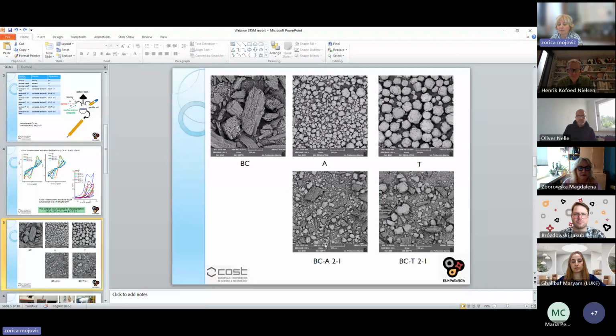These are the results of SEM analysis, and we can see the biochar samples mostly preserved the wood-like structure with agglomerates of about 200 micrometers. The A-type alumina is mostly spherical, while T-type alumina has more crystallized aggregates, but these are composite biochar. And you can see that the aggregates coming from biochar are smaller. The A-type alumina mostly preserved its structure, while T alumina shows a more decomposed structure, more affected by this pyrolysis process.